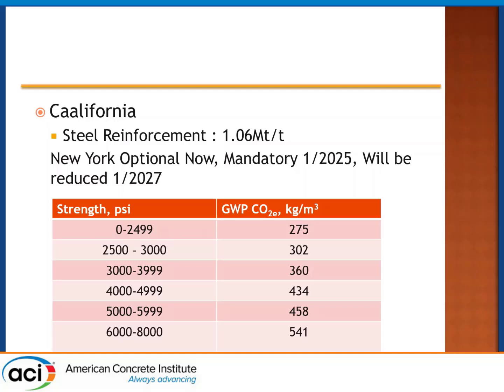Now, there's 1.6 pounds in a kilogram, so in round numbers, let's do 2,500. 302 is about 480 pounds, and a cubic meter of concrete weighs about 2,600 kilograms, so what is that, 2,600 plus 12, it's about 3,000 pounds. So you're looking at about 480 pounds in 3,000 as opposed to the 1.06 or 1,060 you're allowed per ton of reinforcing steel. And so we are having relatively low numbers. But it's getting better. This, by the way, doesn't tell us what the basis is.